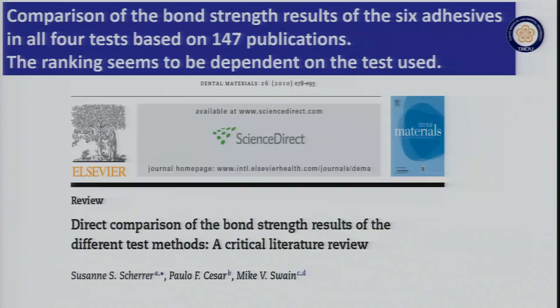Okay, now, nowadays, we have so many excellent papers on the bond strength test using many kinds of adhesive materials. Also, many kinds of bond tests are applied. So many clinicians, not only the clinicians but also the researchers, are very much confused about the results of the bond test. Some papers showed 80 megapascal, the other paper says 20 megapascal, even with the same material. That is because of the difference in the test method.